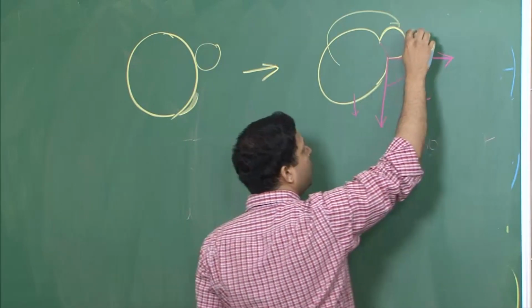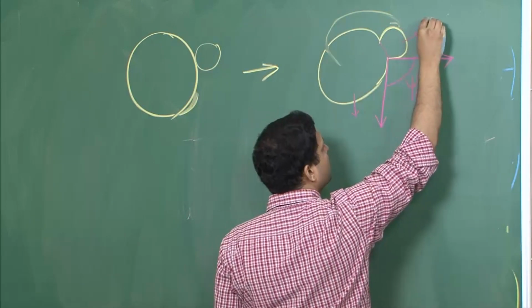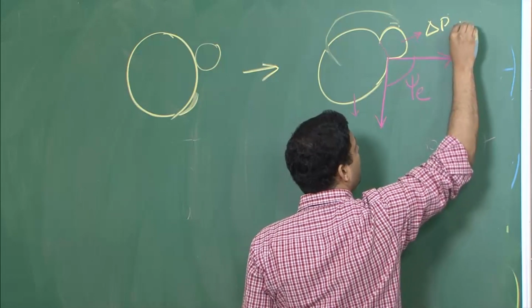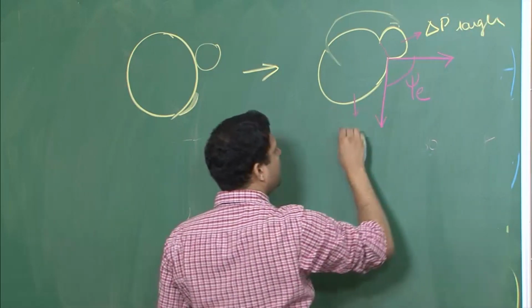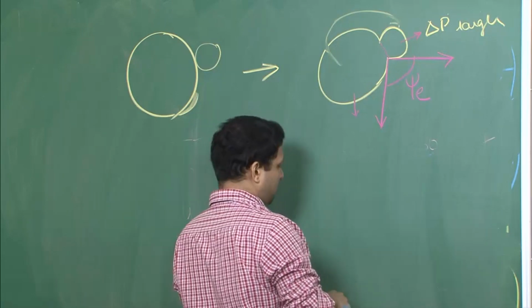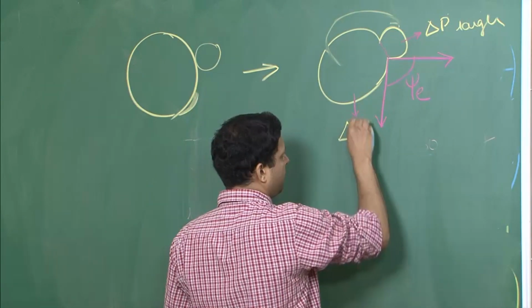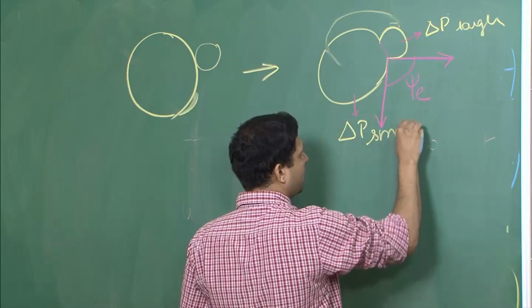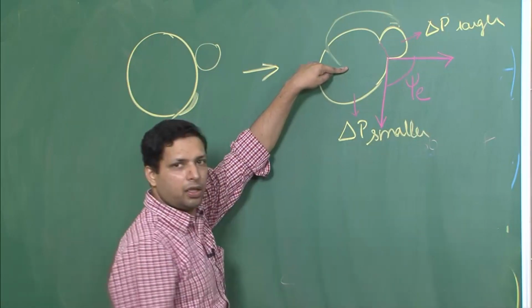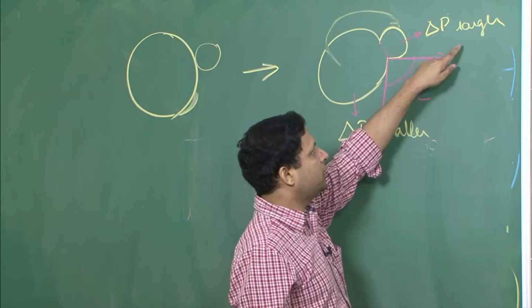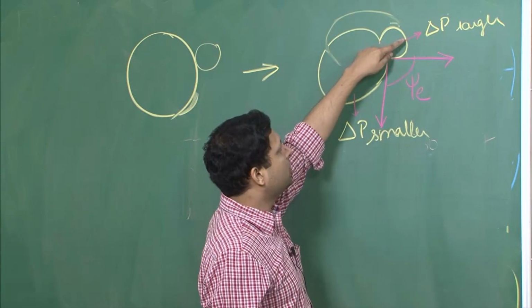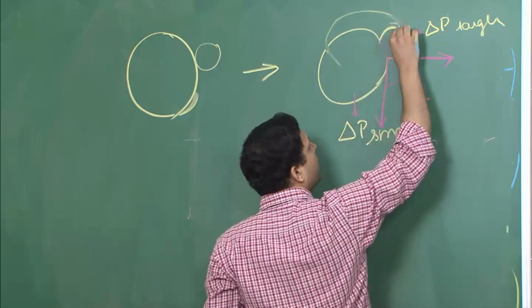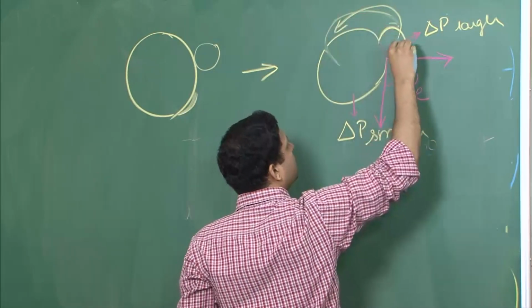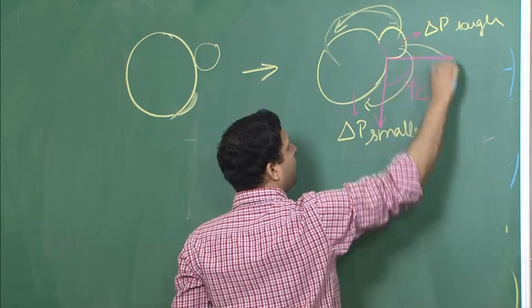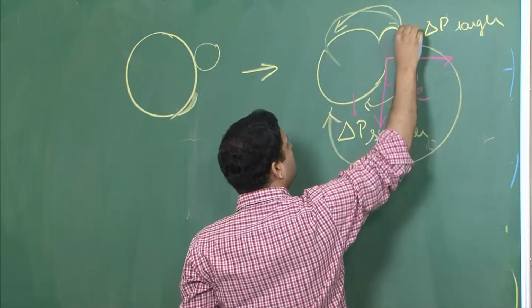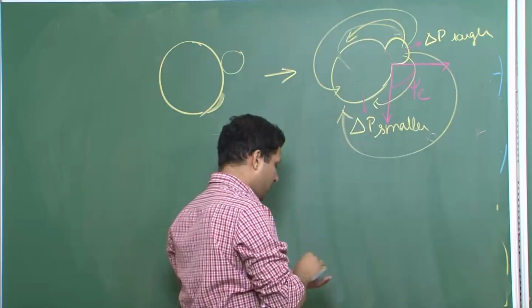I am sorry, the other way around, actually the vapor pressure is larger here, delta p larger, and here it is smaller, because when the radius becomes infinity, delta p is 0. So, smaller the radius, delta p is larger, and therefore, the particles here will evaporate and condense. So, eventually what will happen?